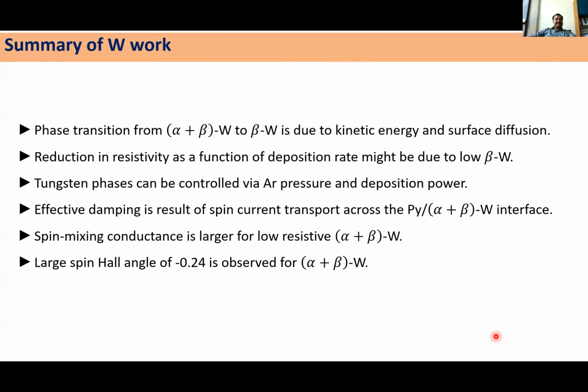So with this, the summary of the tungsten work is that we can see a phase transition from a mixed phase to beta phase when we increase the argon deposition pressure, due to the reduction in the kinetic energy of the atoms because of a higher number of collisions. And we found that the tungsten phases can be controlled both through argon pressure and deposition power. And we can also get a beta phase even above 5 nanometer of tungsten thickness. And finally, we have shown that we can get a large spin Hall angle of 0.24 in a mixed phase tungsten.